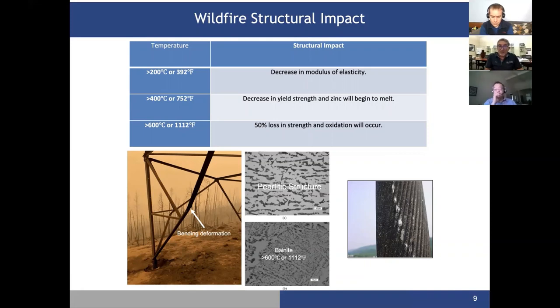At above 600 degrees C, there is a major, unacceptable risk. 50% loss in strength and oxidation will occur. This is irreversible, basically. I have put some examples of what's going on during and after exposure to wildfire on the pictures that you can see on the left side. There is this tower that was exposed to wildfire, and you can clearly see there is evidence of bending deformation and sometimes even movement of these members.